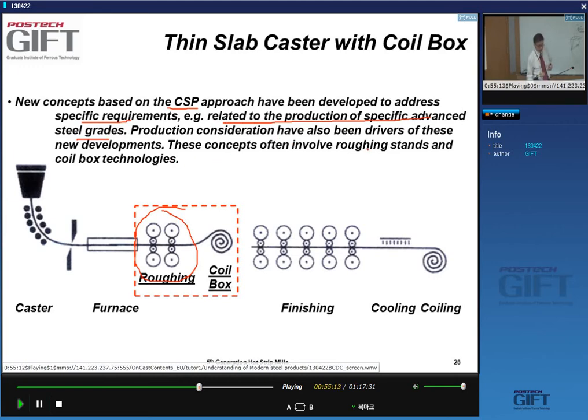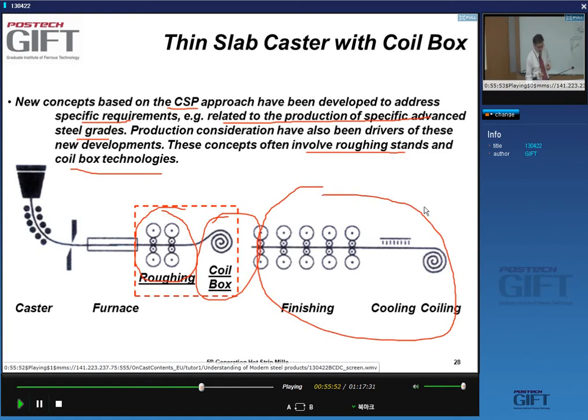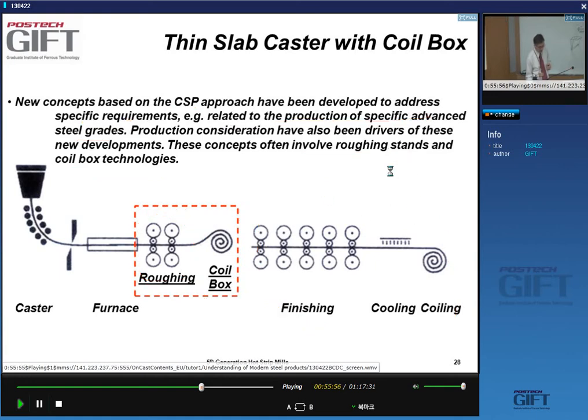And so what we see is the reintroduction of a roughing stand, and instead of using the large tunnel furnaces, the use of coil boxes. Because what does a coil box do? Basically, you get a very homogeneous temperature, and you control the heat loss. So it's a good alternative to a tunnel furnace. Otherwise, again, the finisher, the laminar cooling, and the coiling stay the same. Okay?